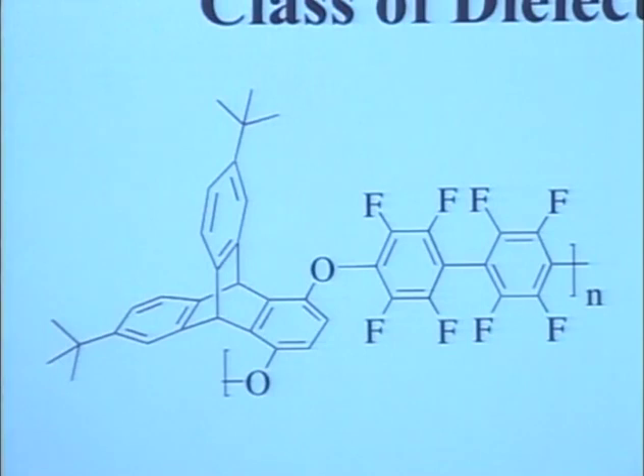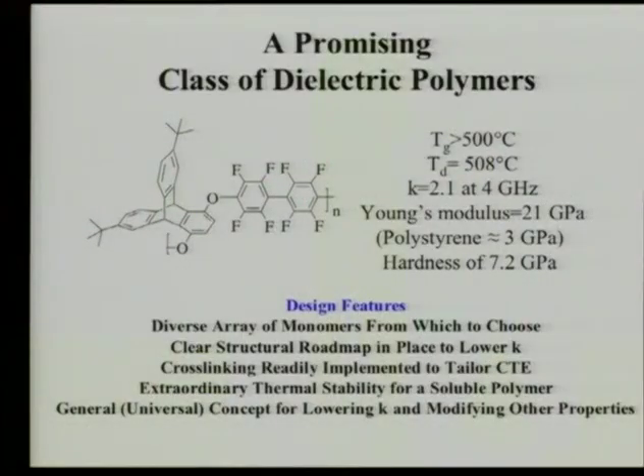And these are materials that, and this is just one of our early examples, have a very good dielectric constant. It's very hard, and it decomposes around 500 degrees centigrade. That's very tough for an organic. My inorganic colleagues always tell me the problems with organics, that they're not stable. Well, 500 degrees is there, and its glass transition temperature is over 500 degrees.